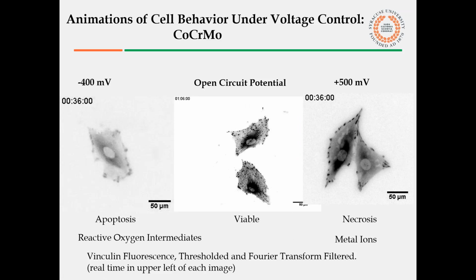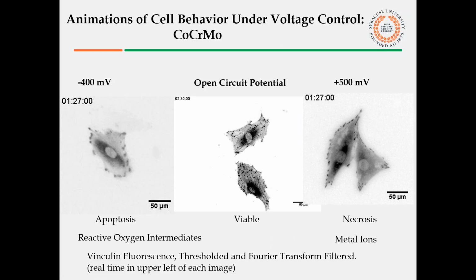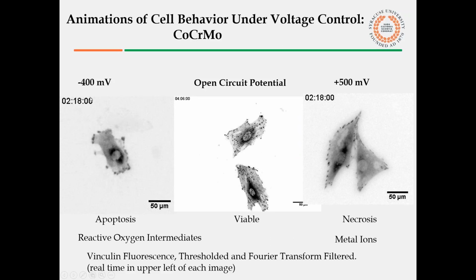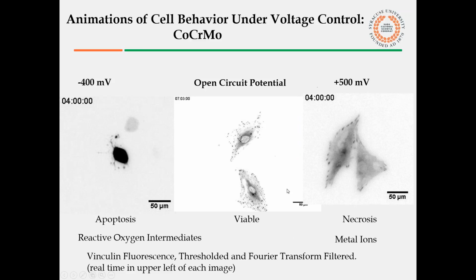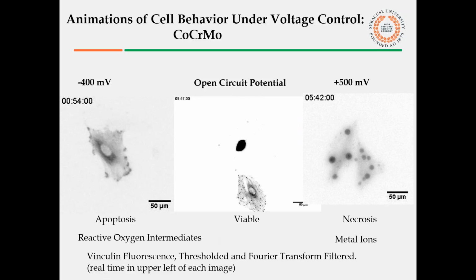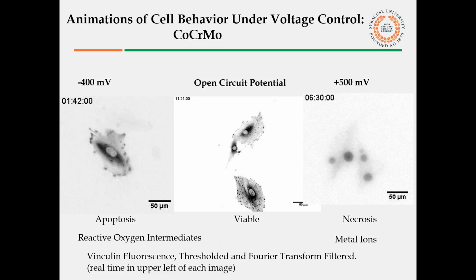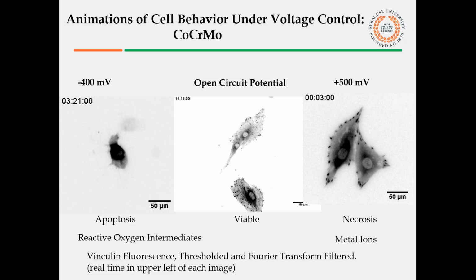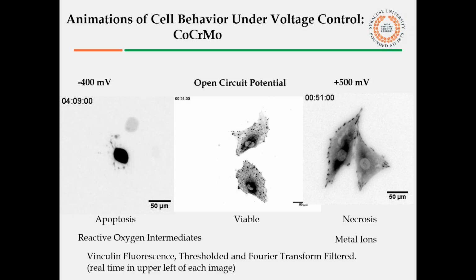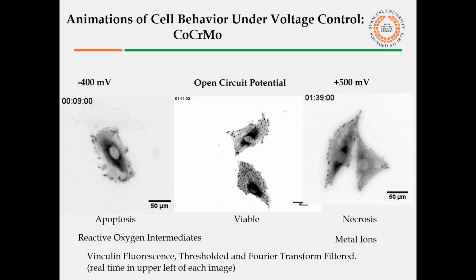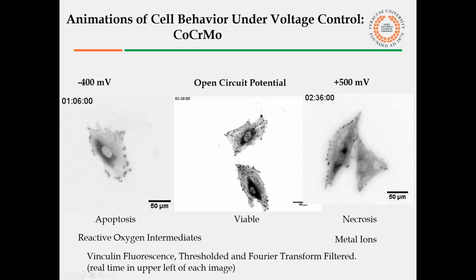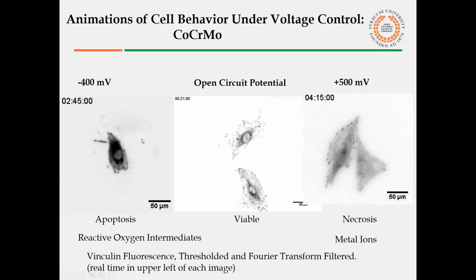These videos that I'm showing are just demonstrating this phenomenon for the minus 400 case, cells at open circuit, and cells at 500 millivolts. What you're seeing is videos that were generated by first creating fluorescent cells that fluoresce their focal adhesion sites, and then monitoring how those focal adhesion sites vary over time as we apply these different electrochemical conditions. So very clearly the cells under cathodic potentials, where you might go from a fretting corrosion reaction, undergo rapid